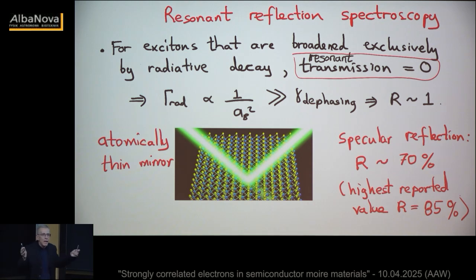We take an incoherent light source, sometimes we filter it down, and then we look at how different frequencies get reflected. Okay? One point that I think I talked about 7 years ago when I was here, and I was excited about it at the time: if you hit these materials at the excitonic resonance, they're atomically thin mirrors. They can reflect a very large fraction of the incident light at the exciton resonance. This is not a typical experimental scenario, but you would routinely get 70% reflection, and the best reported from Harvard is 85%.